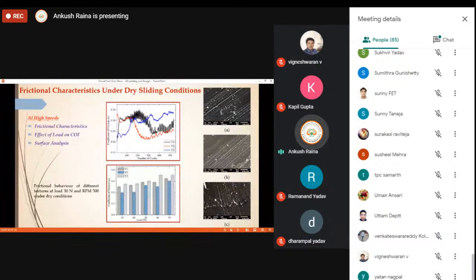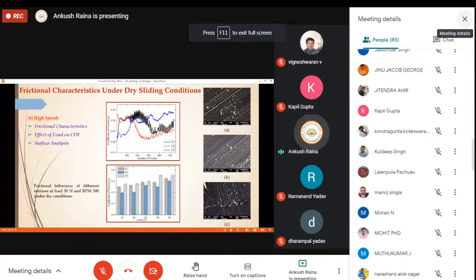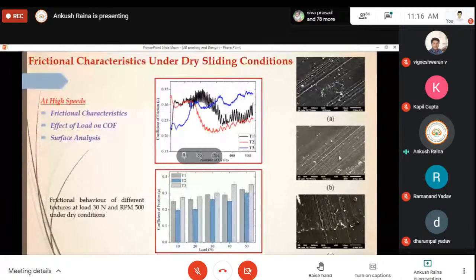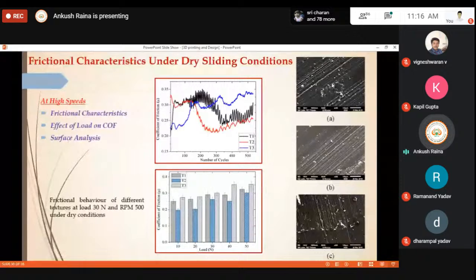But the surface damage is comparatively different from the previous case. This is basically due to the high speeds. More speed means more heating, and due to more heating there will be more adhesion. And what will happen if there is adhesion? The adhesive wear will be more, and the surfaces will be damaged more in comparison to the previous cases, as you can see from these previous figures. But if you compare all these figures, you can see the surface damage with texture T2 is comparatively less in comparison to textures T1 and T3. In textures T1 and T3, you can see there is a lot of plastic deformation, and the material removal in this case is much more in comparison to texture T2.